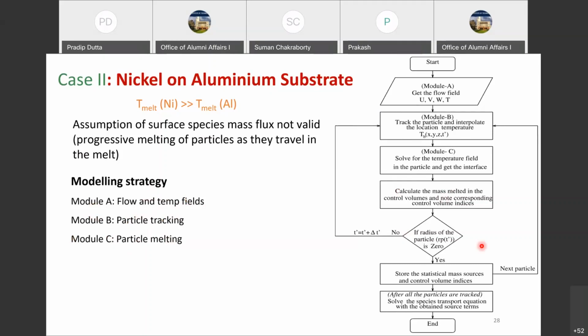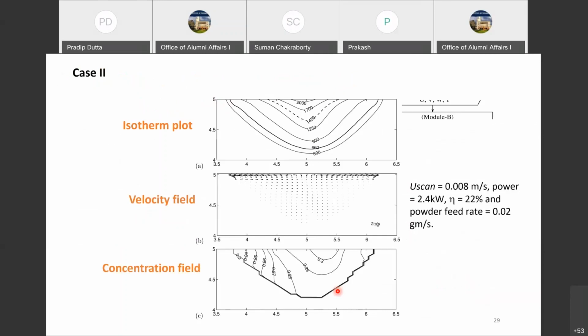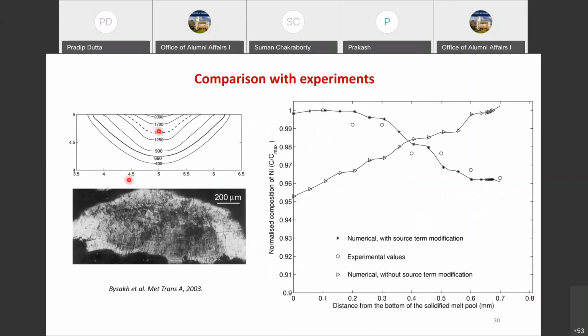So this is the basic strategy that we show. I will not describe the entire strategy in the flow chart, but at the end of it, when we do this process of particle tracking and particle melting, then we have a distributed species mass flux as a source term throughout the weld pool, throughout the melt pool. We have a distributed species source term, and that is very important. Because after we look at the temperature plot, velocity plot, and the concentration field, that is very standard, and of course compare that with some experiments also, the most important part is how the species is distributed in the solidified layer that we see.